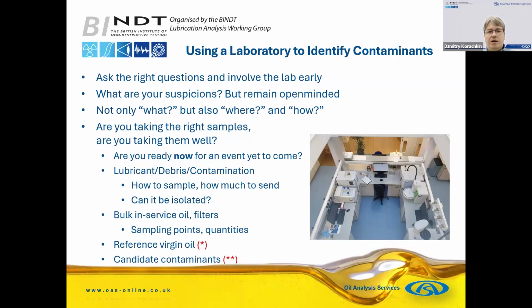But also, as you're listening to and looking at these presentations, you're in a position where you could afterwards take steps to prepare yourselves for when you may need to identify a contaminant and do some sort of investigation, because you want to have clean oil sampling bottles to hand rather than a rinsed out coffee jar or a lemonade bottle, cola bottle, and so on, which immediately introduces a question: the water content we're finding in the sample, is it contamination of the sample, or is it because you had no suitable oil analysis container available and just used whatever was to hand and you rinsed it and it wasn't dried properly?